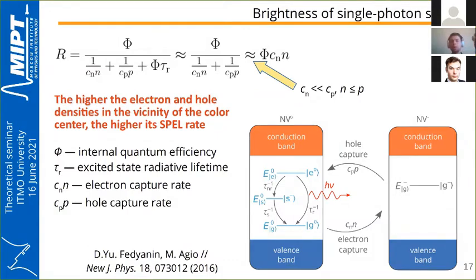For practical application, it's important that our color center is as bright as possible, and the single-photon electroluminescence rate is determined by the expression shown on the slide. It has the quantum efficiency phi, the electron and hole capture rate, and the excited state radiative lifetime. The higher the electron and hole density in the vicinity of the color center, the higher its SPEL rate. So the brighter the single photon source based on color centers in diamond and also in other wide bandgap semiconductors.